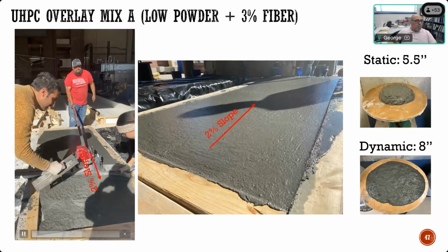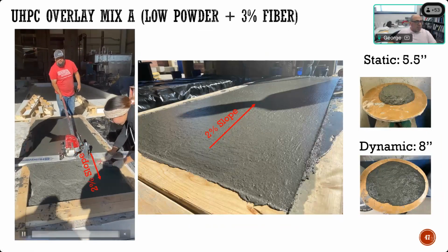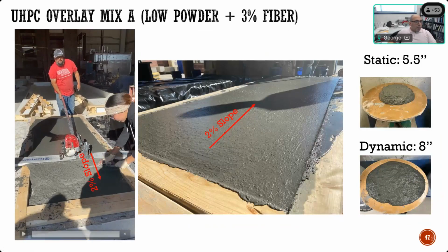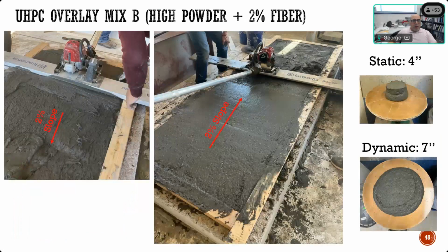And we used a vibratory screed to spread it. You can see how stiff it is ahead of the screed, but before it flows very well and levels very well with the vibratory screed. And that's what we are really looking for, to have a static spread of less than 6 inches, but dynamic of about 7 or 8 inches. So we did that with a mix that has low powder and 3% fiber, and then we did it again for a different mix with high powder and 2% fiber to give the DOT two options and see the performance when we change the dosage of fibers and the powder.